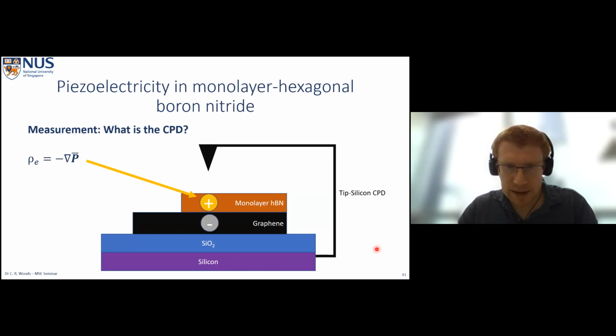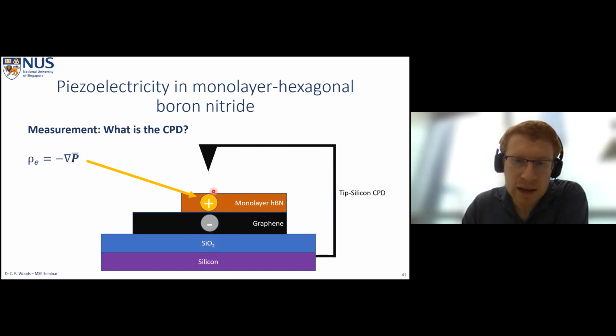This affects our graphene layer, which of course attracts negative charge within the graphene layer. And this creates an out of plane polarization between our silicon backgate and our tip. And this will affect the electric potential between our tip and our silicon, which we see as a different force upon our tip. So this is what's going on in our sample. And so this is our mechanism for observing the piezoelectricity here.